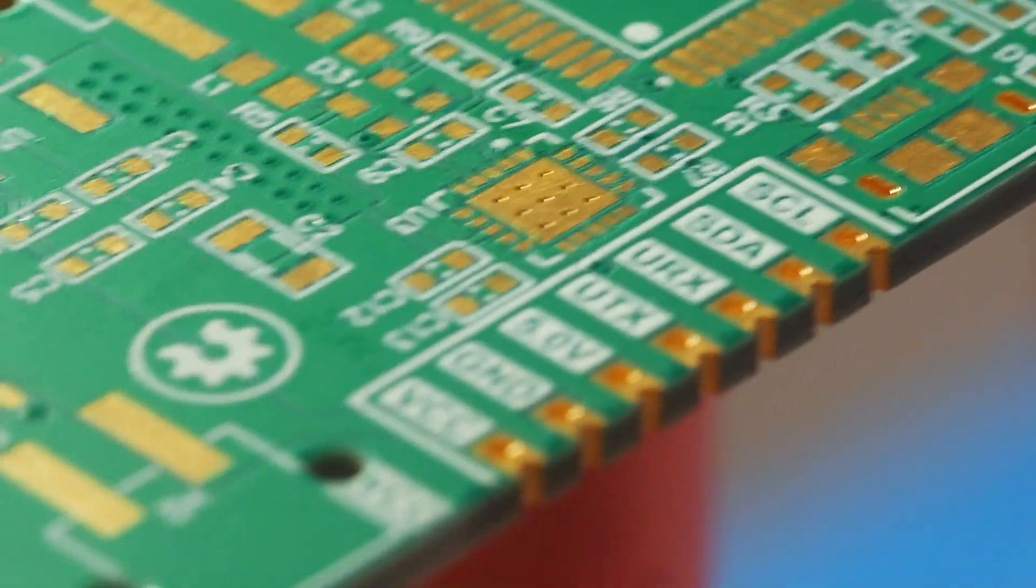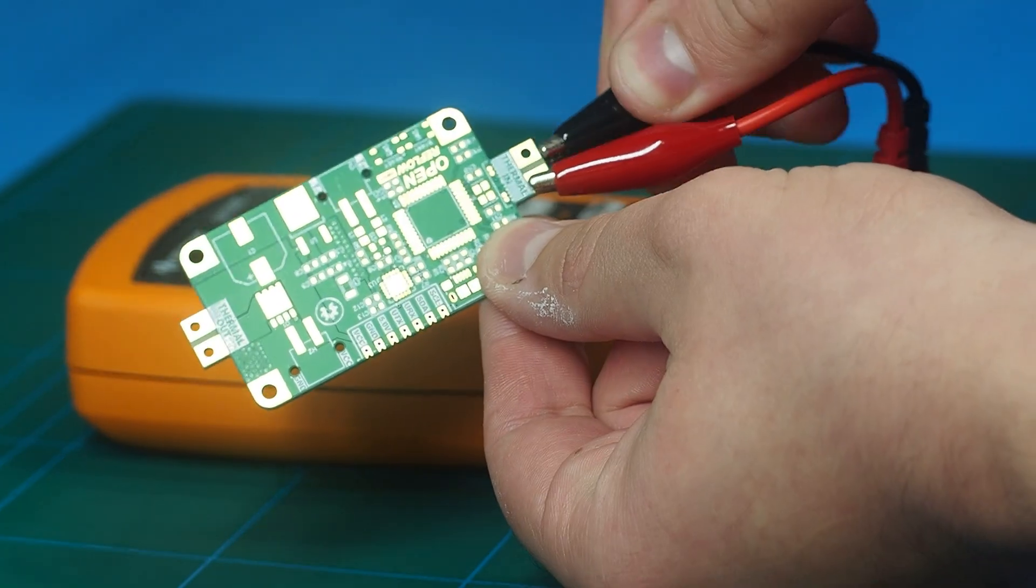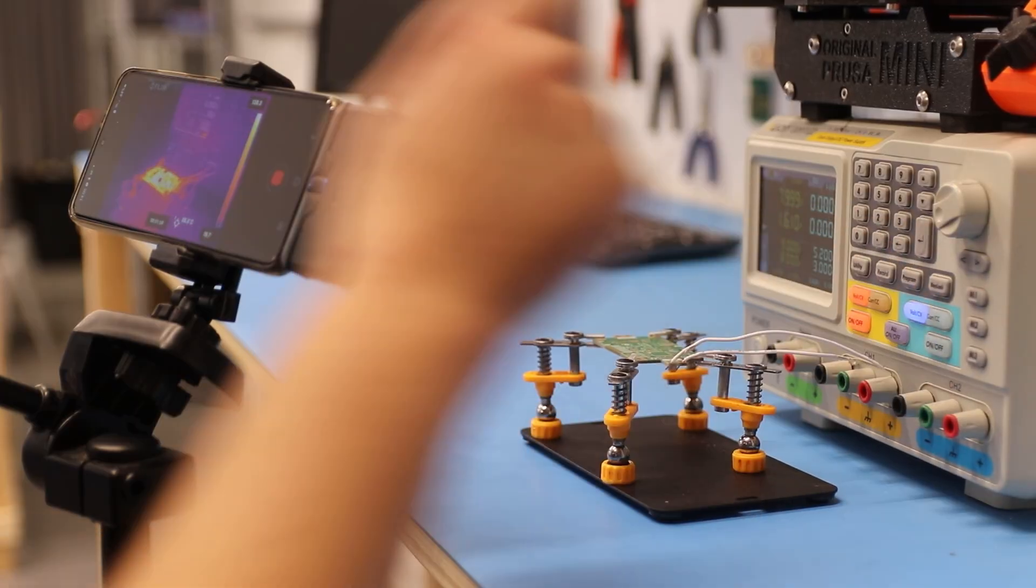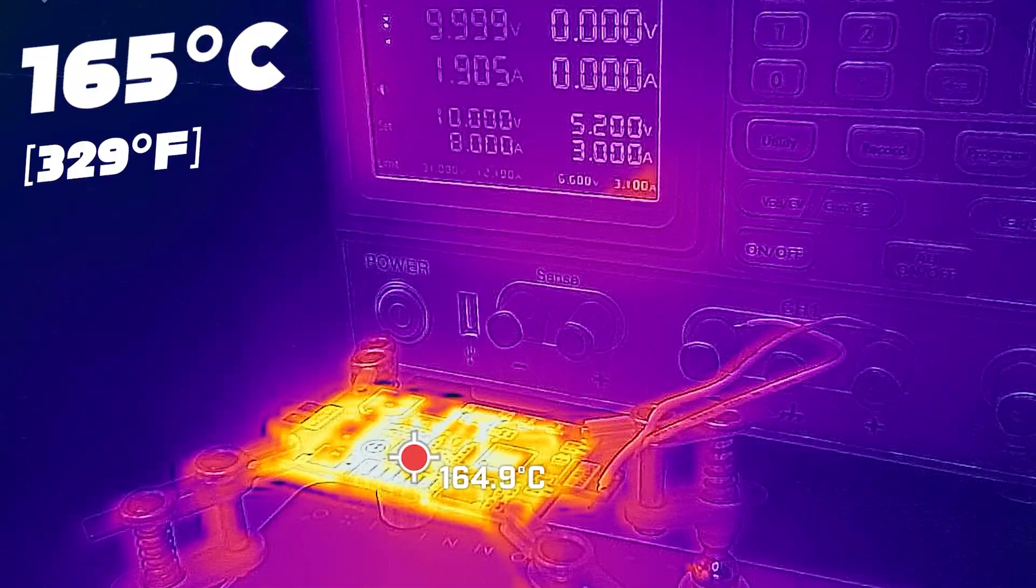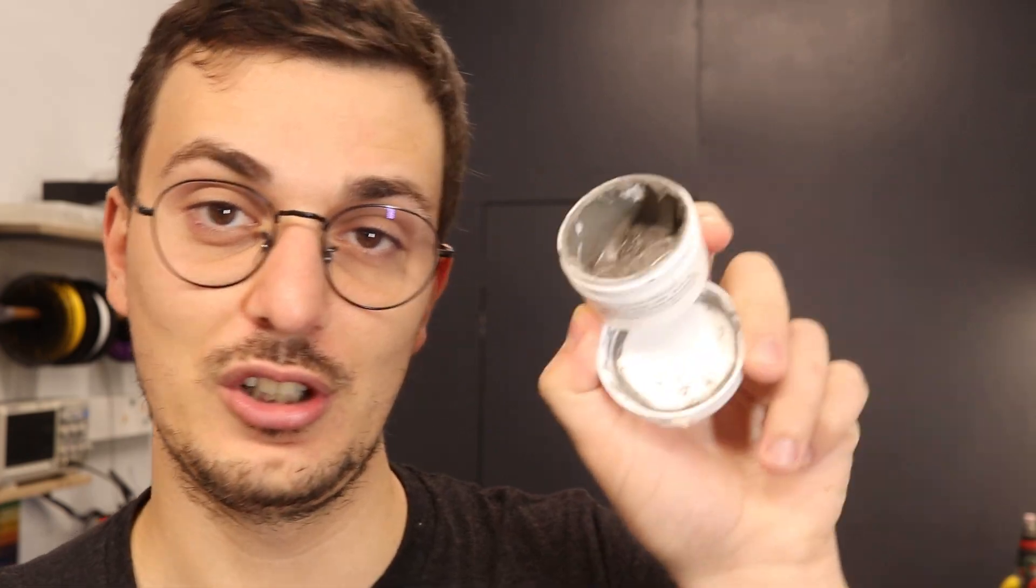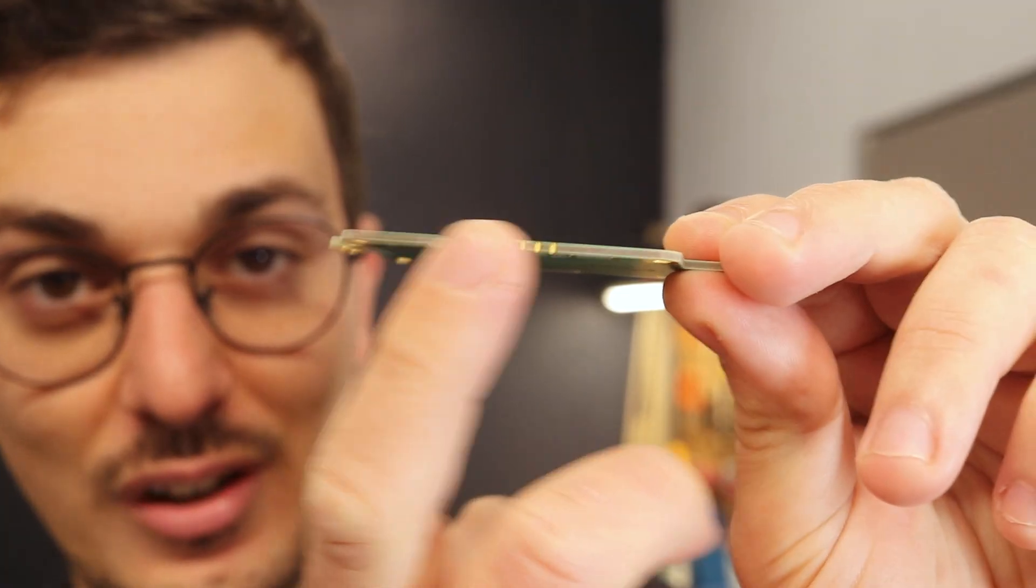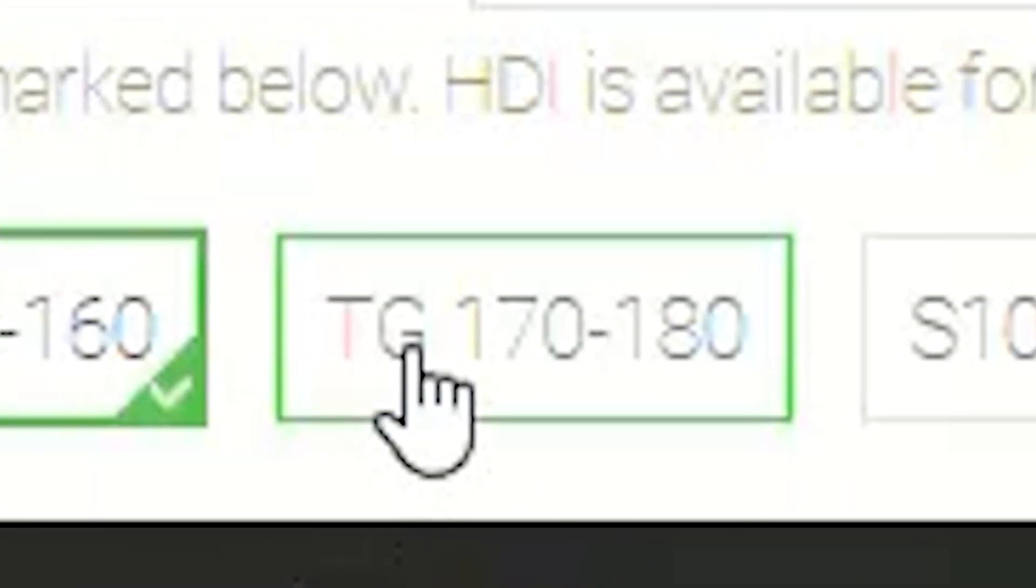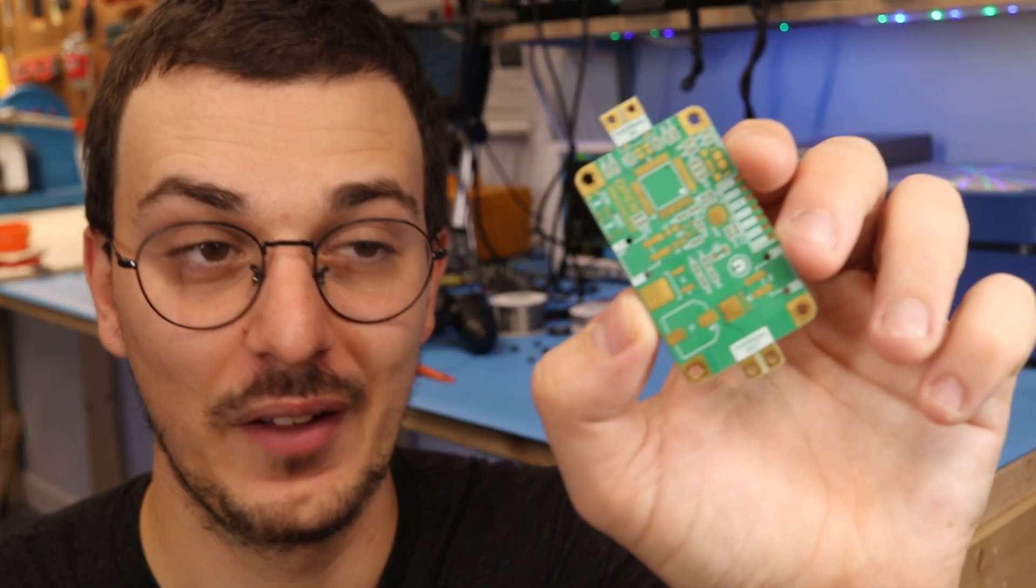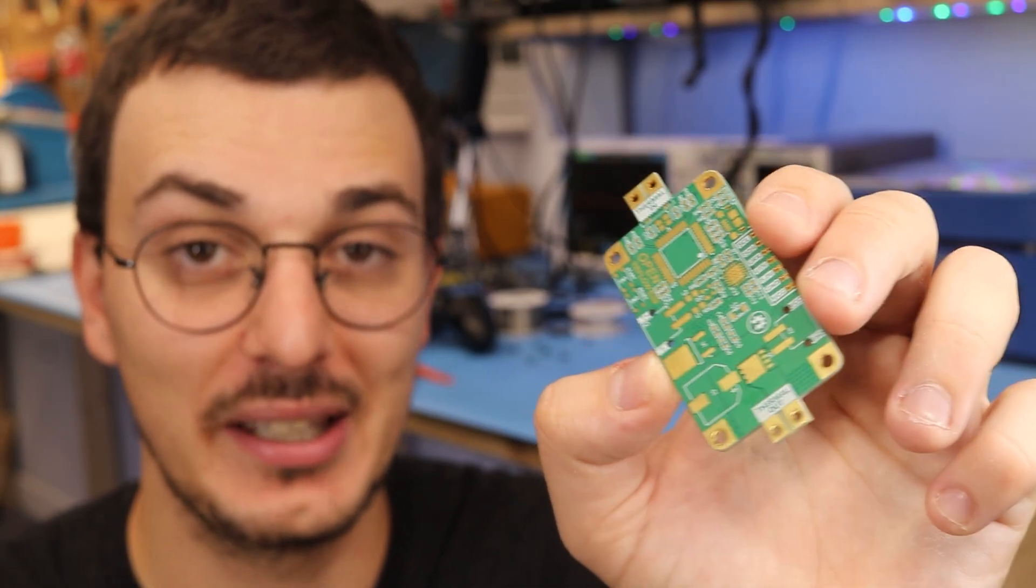So somewhere in there should be a secret heater. The goal was to keep the resistance as small as possible so that it wouldn't need a high voltage to reflow. In fact, it reached 165 degrees at around 9 volts. This is the maximum temperature that the PCB has to reach in order to melt the low temperature solder paste. This may seem a little bit high considering that the temperature has to come from in between the layers, but the PCB has a TG value of 170 degrees Celsius, which is a little bit more pricey. Besides this, the board only has to reflow one time for less than five minutes, so it will be like putting it on a hot plate.